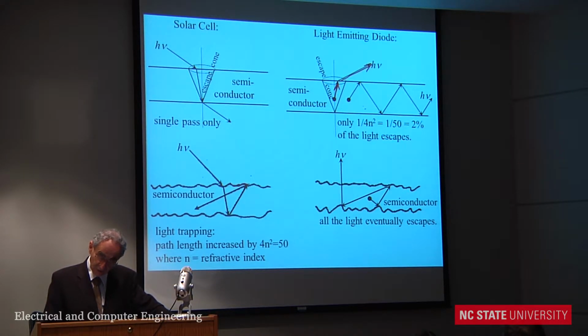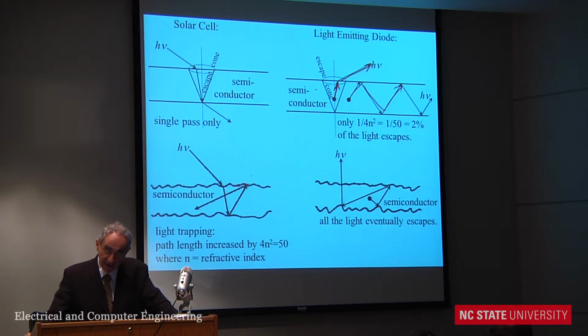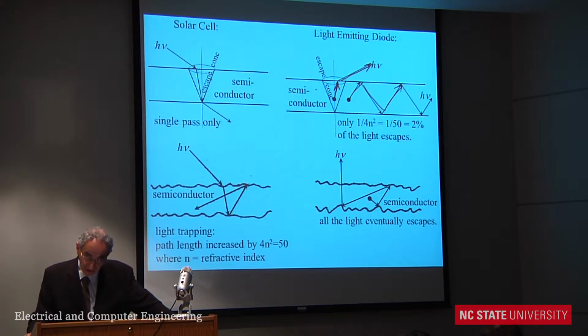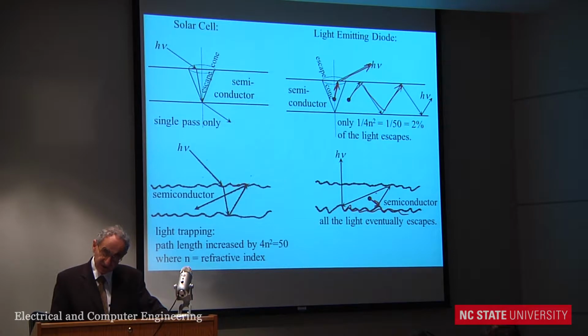98% of the light would just bounce around and eventually get lost because it can't escape. So what they've started doing, and all LEDs do this now, is you break the plane parallel symmetry of the semiconductor. You put in some shape to it, and yes, it bounces around. It still has trouble finding the escape cone, but it has multiple attempts. And finally, after numerous tries, it escapes. And in this way, if you break the plane parallel symmetry, all the light eventually escapes.